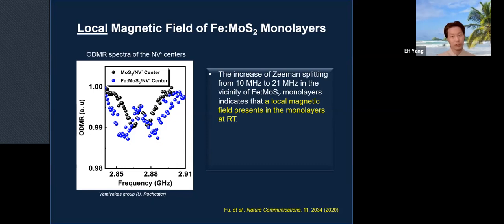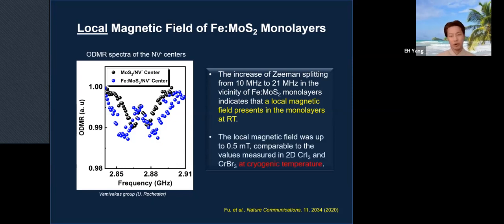And the experiments were done at room temperature, that means the material remains magnetic at room temperature, all right? And the measured local magnetic field was up to 0.5 millitesla, which is comparable to the values measured in 2D chromium iodide at cryogenic temperature. The first sensational paper was published in 2017, right? And that was measured at a similar level of magnetism at cryogenic temperature. Ours is at room temperature, all right?